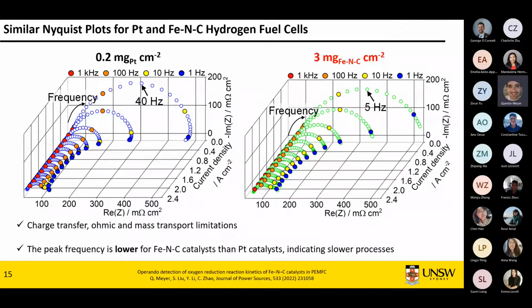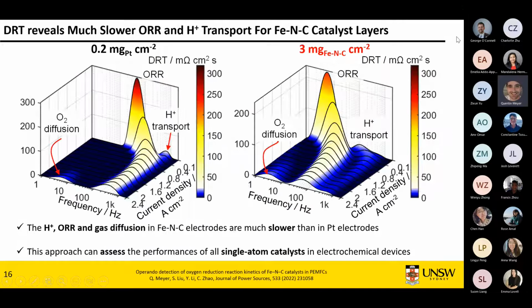What that can tell you right away is that something is much slower in one case than the other one. And that's because you basically have a lower frequency below the semicircle, which indicates there is a lot more stuff happening here. Unlike here, where this kind of frequency is basically all over this region. So it doesn't really tell you what's going on, just that you're looking at something that's slower in one case than the other case.